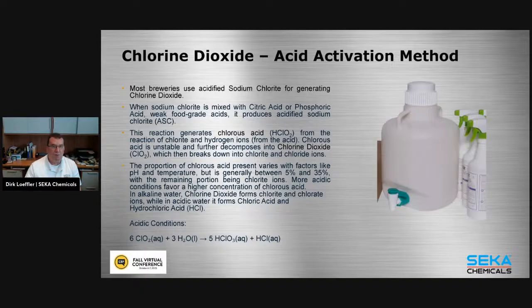The problem is, when you do this in acidic conditions, you also end up with hydrochloric acid in the breakdown process, which, again, is not good on stainless steel. So if you leave this sitting in your equipment, not a good idea. This is a big no-no. Do not use chlorine dioxide as a no-rinse sanitizer ever on stainless steel, because you will pit your equipment. There is no if or but, there's only yes.